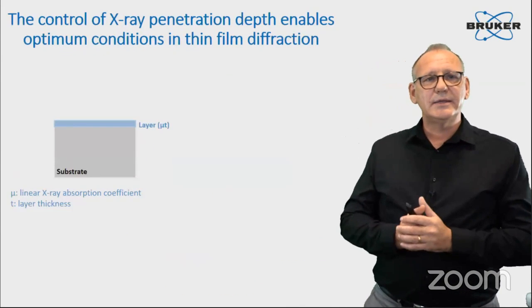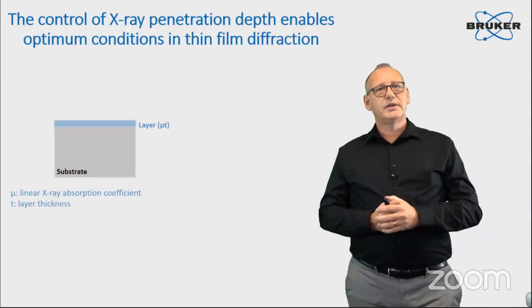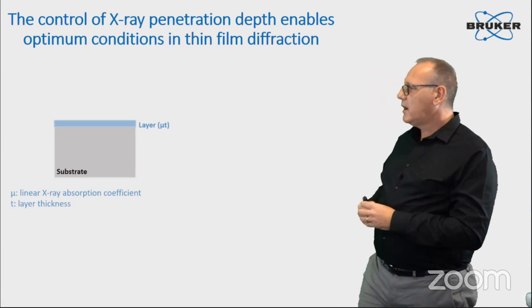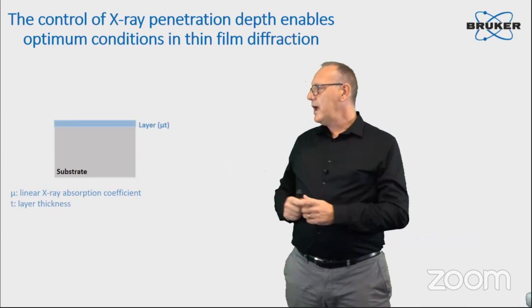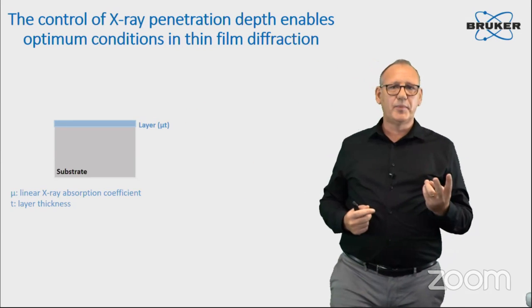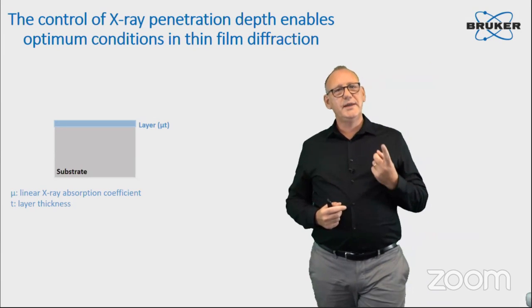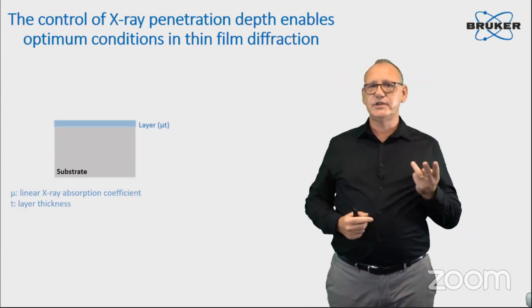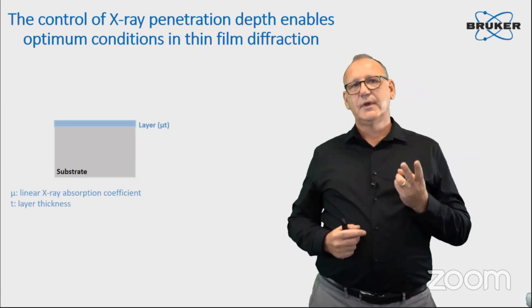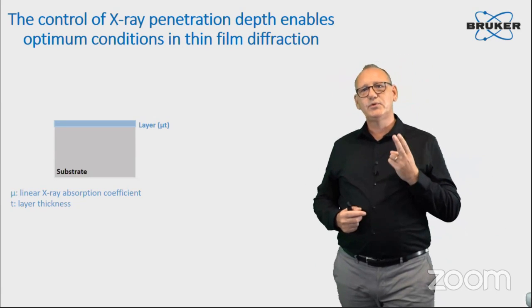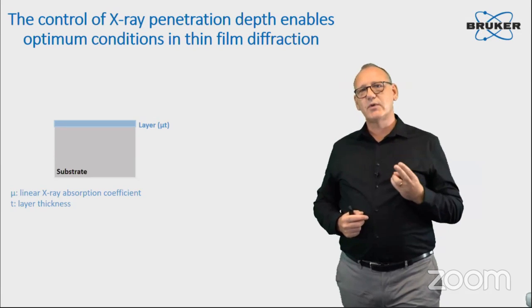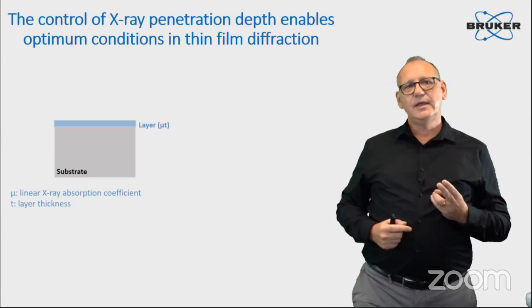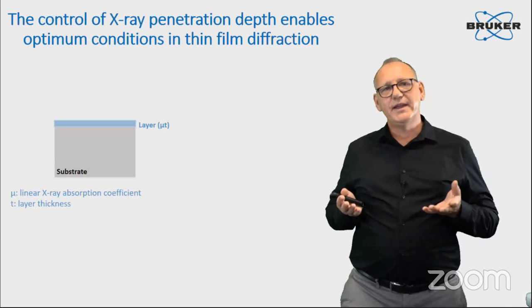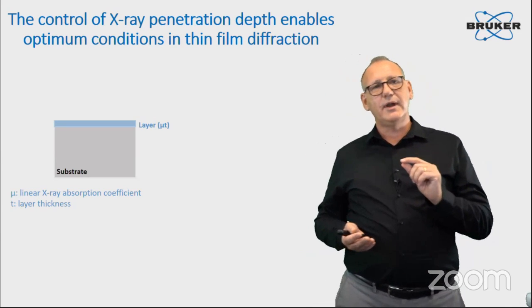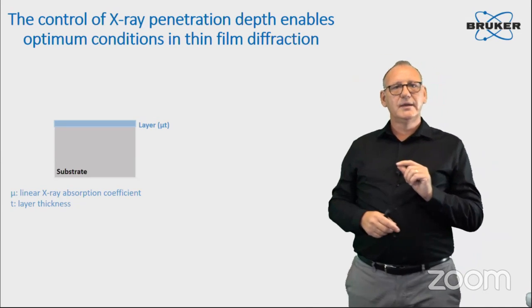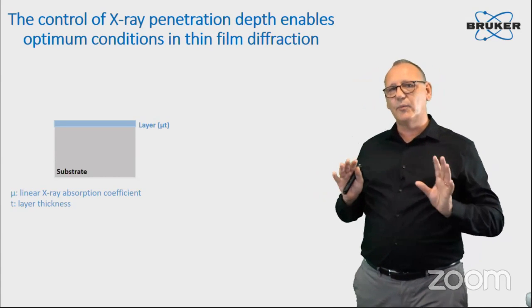So why is thin film diffraction so challenging? You have here a thin layer, and the layer is characterized by basically two parameters: mu, which is the linear absorption coefficient, and T, which is the thickness of the layer. The product of those two will help you understand how deep X-rays will penetrate into the material. If you have a denser material, it will penetrate less. If you have a thinner layer, it will go through very easily. So these are parameters to take into account to optimize your measurement conditions.